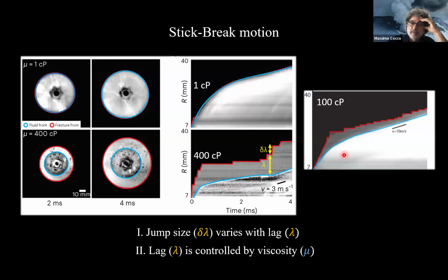Yeah, thanks. Okay. And the expansion rate is not constant. At the beginning, the fluid expands very, very fast. So this is the high slope, and then it slows down a bit. But it's a radial crack, so I guess it makes sense. The larger the crack, the more differential volume you are freeing for every delta R, right?